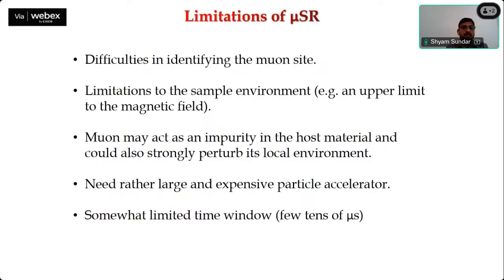But this is not very comprehensive. There are a few more things you can do with the MUSR, which I don't have enough time to cover, each and every topic. But before completing this part, I just want to say, like any other experimental technique, the MUSR also has some limitations. For example, it has difficulties in identifying the muon site. So basically, when the muon enters your sample, it doesn't go randomly to any place. It goes to a highly symmetric site in your sample, but not all crystal structures are very easy. And so sometimes it is difficult to find out where your muon is going in the material. And there is a limitation to the sample environment, for example, an upper limit of the magnetic field. You cannot apply a very large magnetic field.